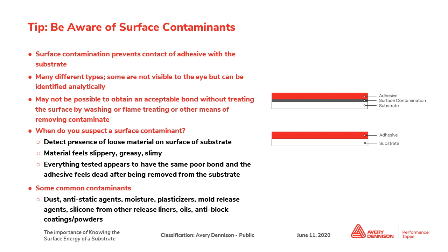And the first thing I do is ask, actually, hey, did anything change with the customer's situation? And a lot of times what we find with these mold release sprays is that the mold release operator had left the company and a new one had joined. And this new operator liked to use a heavy amount of mold release spray on the mold, and it was transferring over to the plastic. So we have to be aware of those types of things. And sometimes it's hard to see, and we have to troubleshoot it out.